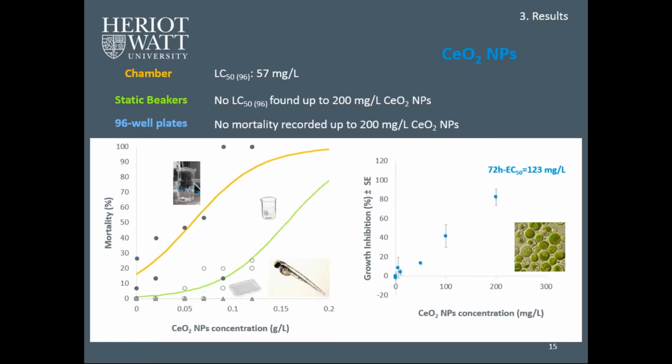The cerium oxide nanoparticles, we see the same pattern. The toxicity produced inside the chamber is higher compared to the static methods. So we have in the chamber an LC50 of 57 milligrams per liter. We didn't find an LC50 in the static beakers, and there was no mortality inside the 96 well plates.